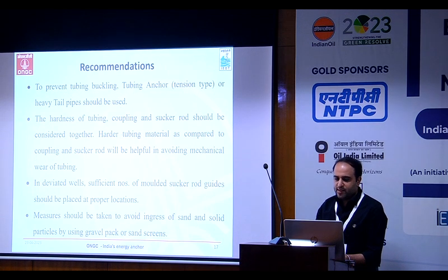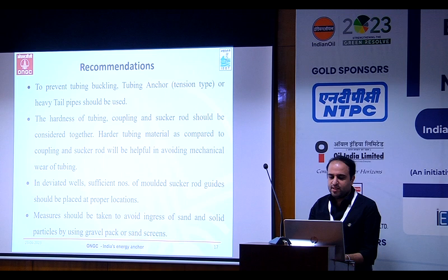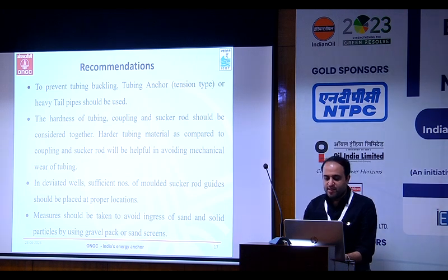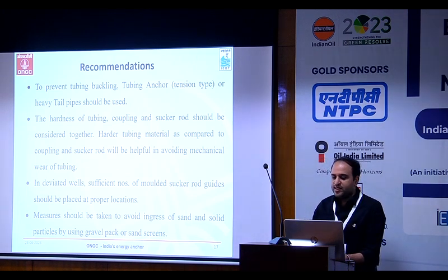To prevent this, we recommended using tubing anchors, which prevent the buckling of tubing in such deviated wells. Also, the hardness of tubing and sucker rod should be considered, because the tubing should be harder than the sucker rod. In this case, the sucker rod was actually harder than the tubing. Also, in deviated wells, a sufficient number of molded guides should be placed at proper locations, and to avoid sand, gravel pack or sand screens should be used.